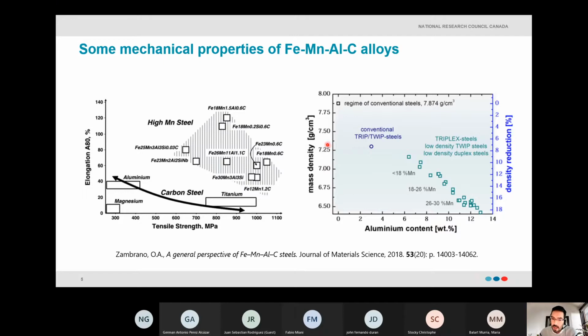Here is a graph of the mass density versus aluminum content. And of course, as we increase the aluminum content, we will have a drastic decrease in the density. So we can achieve density reductions of about 18%. That means close to 6.5 grams per cubic centimeter, when compared with the conventional steels at 7.8. So we have a really interesting effect of the aluminum in these alloys, and that's the main reason that these alloys are called lightweight steels.